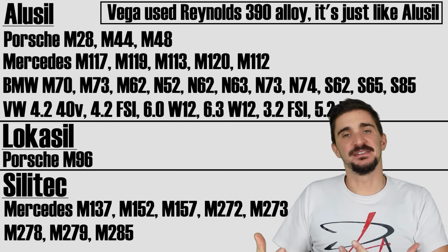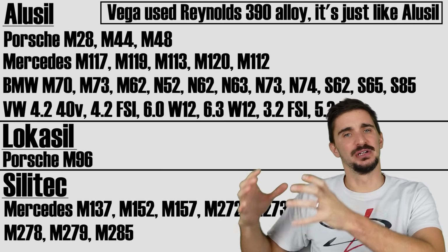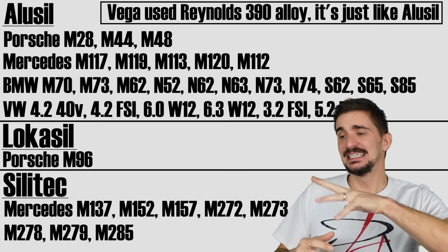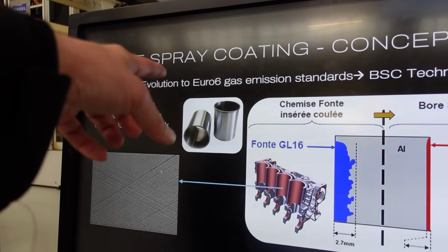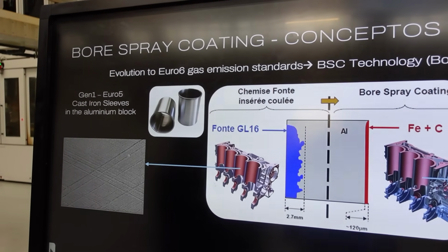Now, despite the reliability failure of these coatings, it is undeniable that a thin coating has many benefits over a thick iron liner. And so manufacturers did not give up. They decided to try to find a new way to avoid cast iron liners, and what they did ultimately and finally is that they gave up on all the etching and the scratching, and they decided to spray the cylinder liner onto the block. And that is the exact process that I got to see when I visited the Horse Valladolid factory in Spain. It is called bore spray coating.